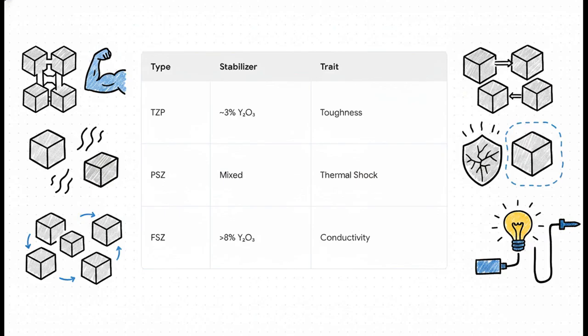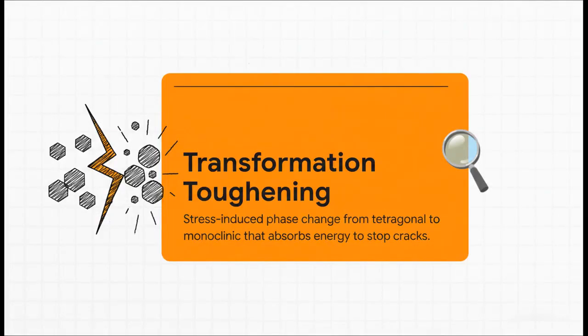And finally, if we flood the recipe with, say, 8 to 10% yttria, we get FSZ, fully stabilized zirconia. This is mostly cubic. Now, it loses its crazy toughness here, but it gains incredible ionic conductivity, which is a neat party trick we'll talk about in a minute. But going back to TZP and PSZ, why exactly are they so unbelievably tough? It all comes down to a phenomenon known as transformation-toughening. By carefully engineering the ceramic, scientists leave those tetragonal grains in what's called a metastable state. So they're sitting there perfectly comfortable at room temperature, but they are just waiting for any excuse to pop back into their larger monoclinic shape.